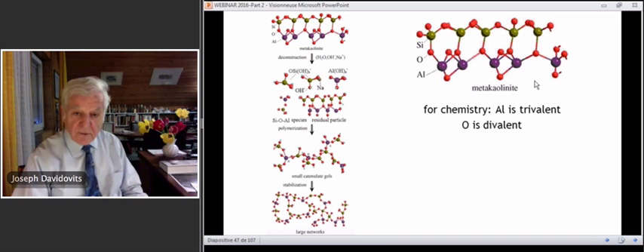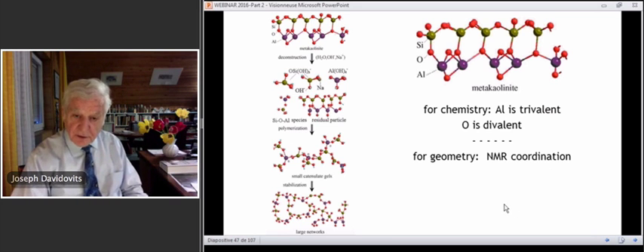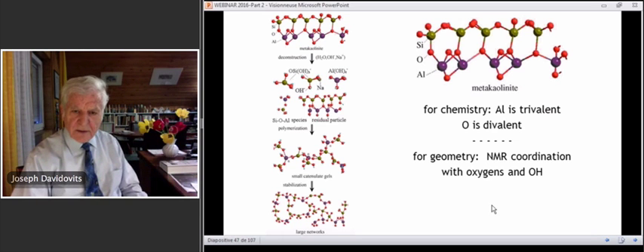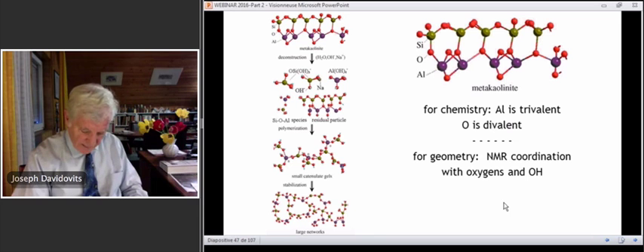Worse than that. For chemistry, oxygen is divalent. That is, one atom of oxygen may only be connected to 2 other atoms. And what we have, oxygen connected to 1, 2, and 3. This is chemistry. For geometry, that is based on coordination, it is different. It is the coordination that is surrounded by the oxygen. We don't take any account about the chemical reactivity. We don't care.